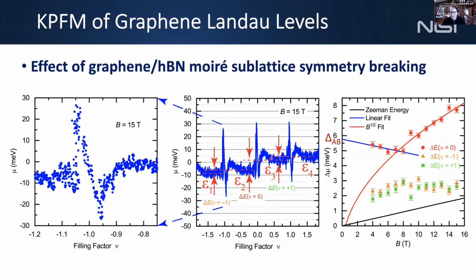If we look at E3 minus E2 across the n equals 0 Landau level, it is the largest energy scale here. So that's consistent with, like, a valley polarized gap. It goes up as the square root of B, like you'd expect for interaction physics, but then it kind of turns around here. And remember, I told you we have a zero field gap, a sublattice symmetry gap due to the Moiré superlattice. And so we know that at zero field, this curve has to go somewhere on this axis, up here. So this gives us more information on how this should behave.